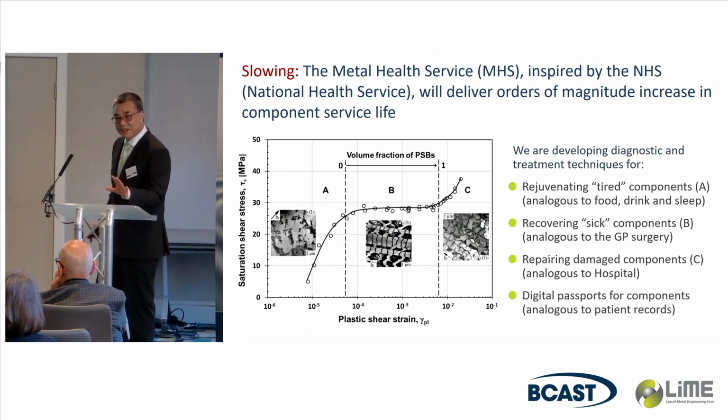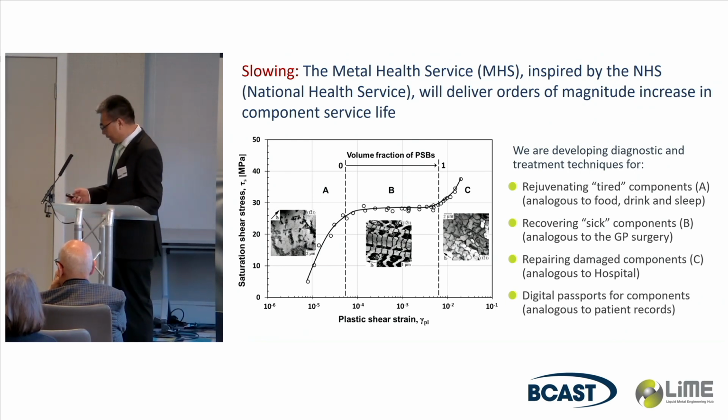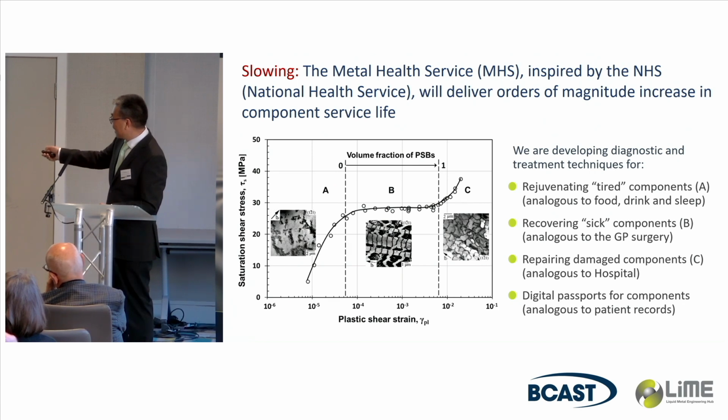Finally, very quickly, we are working on extension of life of metallic components, inspired by the National Health Service. We're going to create a similar thing for metals, and we treat metals as friends rather than slaves, so they have multiple lives. Here is the flow curve for fatigue. You can see the first stage has dislocation tangles, second stage, B, you get slip bands, and crack initiation is the last stage here.